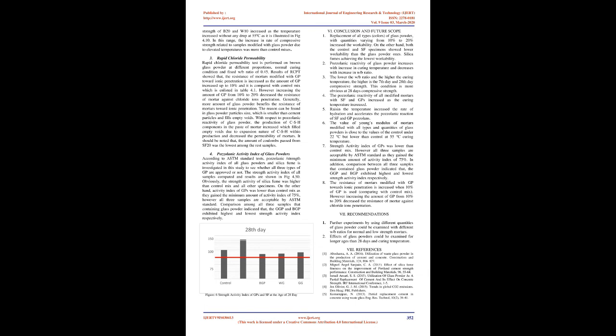Generally, more amount of glass powder benefits the resistance of mortars toward ionic penetration. The reason can be found in glass powder particle size, which is smaller than cement particles and fills empty voids. With respect to pozzolanic reactivity of glass powder, the production of CSH components in the paste of mortar increased, which filled empty voids due to expansion nature of CSH within production and decreased the permeability of mortars. It should be noted that the amount of coulombs passed from SF20 was the lowest among the rest of the samples.